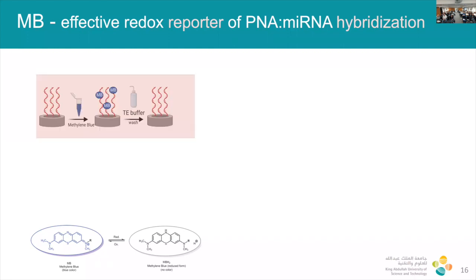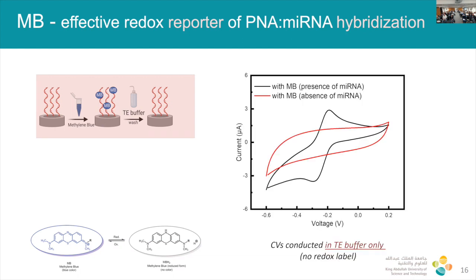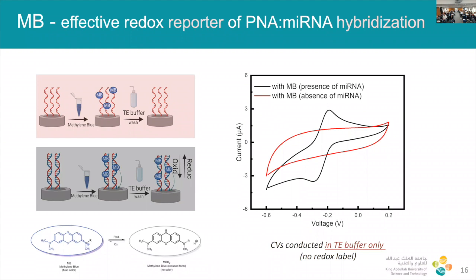Of course, we want to do our controls. So we have just PNA on the surface, we incubate with methylene blue for just 5 minutes, and then we wash off. What we expect is the methylene blue is not going to interact with our PNA, and it's just going to wash off very easily from the surface, and we expect to see nothing, right? We expect to see no curve whatsoever, and that's shown in red. So we don't see any oxidation peak because there's nothing really redox active there. And then what happens if we add our target microRNA, it hybridizes to our PNA. We then add the methylene blue. It intercalates specifically due to the presence of a duplex. And then we run the same CV in TE buffer. The only redox active molecule is the methylene blue. It's only there because we have the duplex form. So you can see a really nice peak here that corresponds to the oxidation potential for methylene blue.